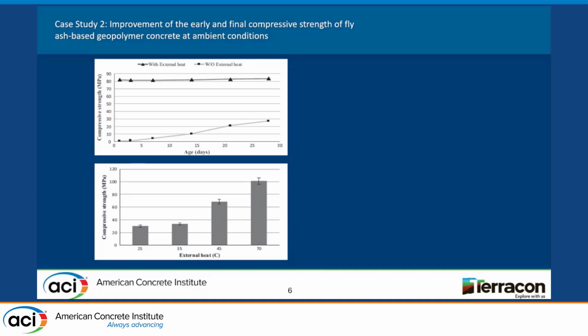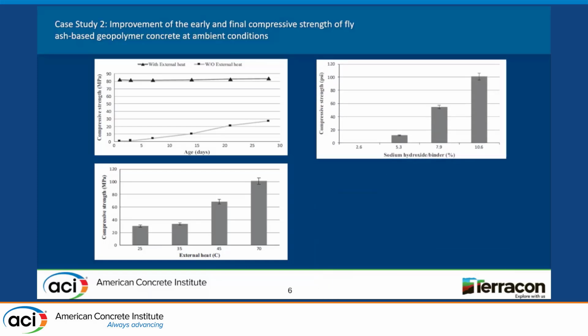So then I wanted to see, how about if I reduce the external heat? How about reduce it from 70 Celsius up to 45, which is 120 Fahrenheit, or up to 35 and up to 25. And you can see here the compressive strength, once I reduce the external heat, the compressive strength also reduced due to that.